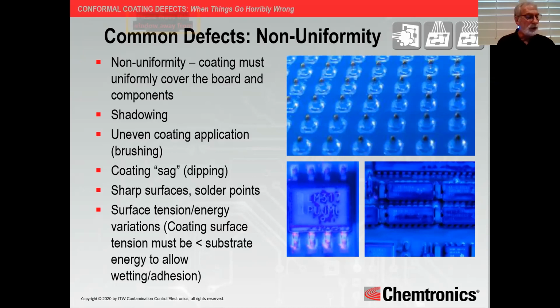If you have any uneven coating application, that could be cause for concern. Brushing is an example of this. When you're using a brush to apply the coating, you're generally going from the beginning of your pass to the ending of your pass on that brush stroke. You're going to apply more coating at the beginning of the pass and less coating at the end of the pass.